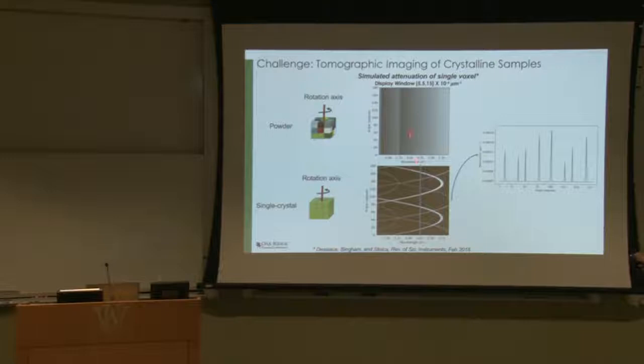That's typical. So that is very typical for most X-ray CT applications, not just for neutrons, even for X-rays. But if you take a single crystal and do the rotation, then the attenuation is going to suddenly change at certain wavelengths and angles because Bragg's law gets satisfied. So what happens is, doing computed tomography of samples containing single crystals is much more difficult because if you plot how the attenuation changes as a function of angle, let's just take one wavelength. So if a neutron beam, many energies, pick one wavelength and look at how the attenuation changes.